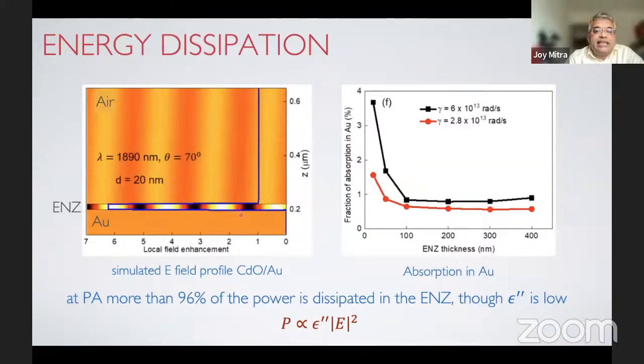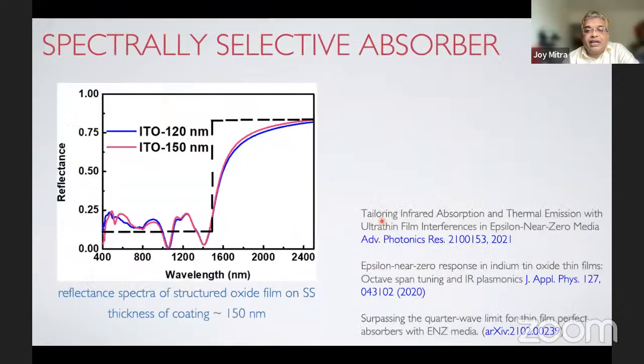And what we see is that the electric field is highly enhanced. If you do the power calculation, we see that less than 4% of the power is dissipated in gold. Less than 4% is dissipated in gold at perfect absorption. The rest, 96% of the power, is actually absorbed by this very thin ENZ material. Okay, and that is a real selling point of this story. In terms of, I'll just end with the spectrally selective absorber. So you have directionality.